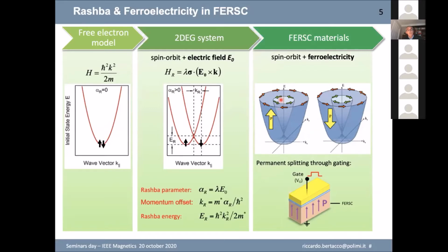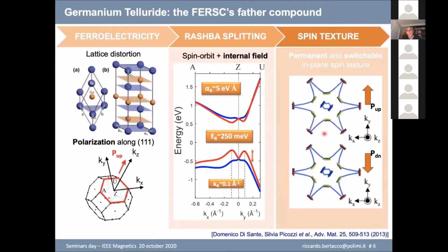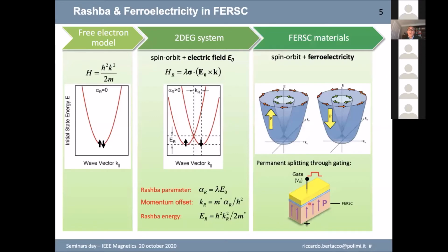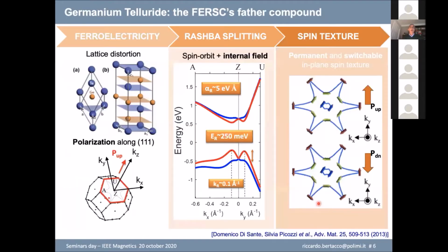In these materials, the beauty of the story is that the way you break the inversion symmetry and give rise to the Rashba effect is the fact that you have a polarization, which is a non-volatile entity, so that you can now play with the polarization. When the polarization is upwards, the sense of circulation is clockwise in the outer band. If the polarization becomes inwards, pointing downwards, you see that you reverse the sense of circulation. And the idea was, okay, we can play with these materials in order to realize devices in which you have a gate, you control the ferroelectric polarization, but this means that you are controlling also the spin. It's a way of controlling the spin texture with the ferroelectric polarization. What about germanium telluride?